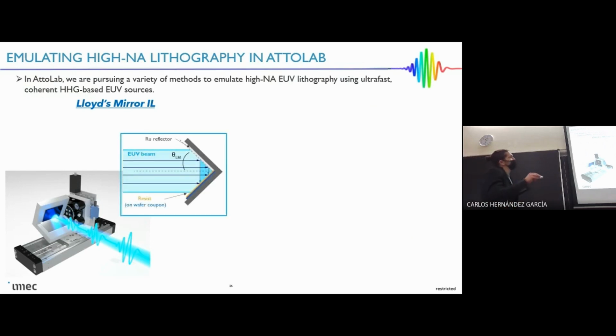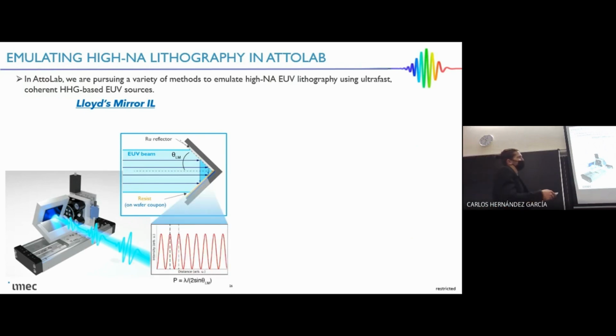So what this looks like is we have our reflector here. We use ruthenium because of its good reflectivity at 13.5 nanometers. We put that at a right angle with the photoresist material, and by adjusting the relative angle of this holder, here you can see a rotation stage with the EUV light, we can get a partial reflection that then interferes with the main beam on the photoresist here. And what that does is that creates a linear grating.